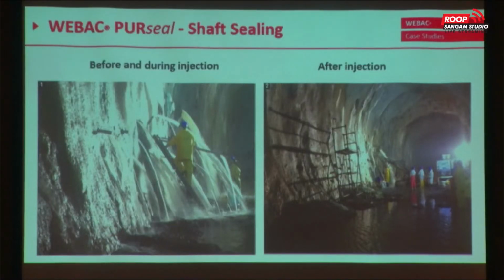So we decided, we talked with the designers and with the owner, and last but not least, that was also injected, but with some technical accessories we applied. First, they applied a huge, thick metal plate on top of it, where we installed a huge ball valve in the middle to release the water pressure. And then we drilled from each angle as good as possible, as deep as possible, to inject the cement and to inject our polyurethane. And after that, they applied also shotcrete on top of it, so it is done. We closed that ball valve step by step. If you see some progress, and with luck we get this done, but this was really a hard fight against the water stream there.